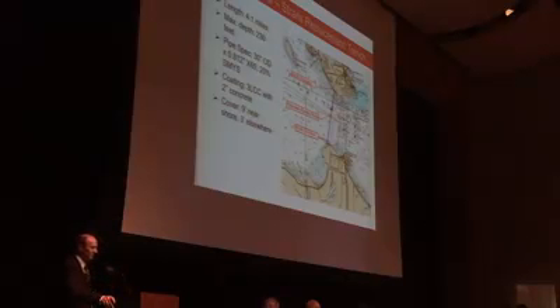Alternative 4. Under Alternative 4, we were tasked with providing a hypothetical replacement option for the Straits pipeline, utilizing best practices technologies. And so Alternative 4A looks at conventional trench installation. It's 4.1 miles in length, goes through about 230 feet of water, 30-inch single pipeline, 30-inch, 0.812 inches in wall thickness, material grade X65, which operates at about 20% of its yield strength. For the purposes of fleshing out this analysis, we considered that that hypothetical pipeline would be coated with 3-layer composite coating and that it would be buried throughout its crossing. So about 9 feet of burial depth near shore and 3 feet of burial elsewhere.